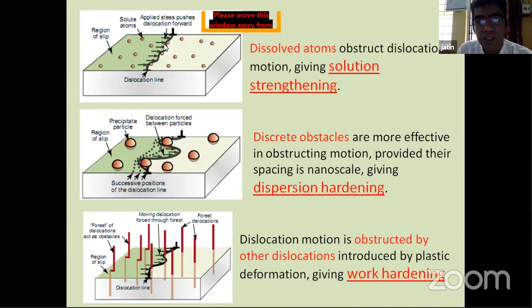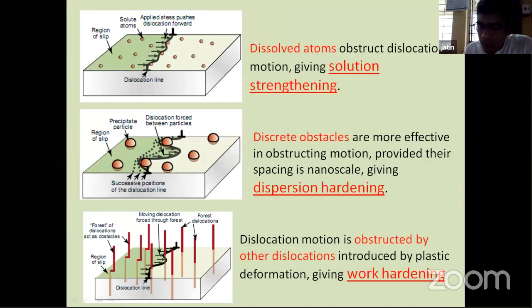Now there are three ways by which this is happening. Either your atoms are dissolved, but they do have some physical features present inside the material. When you deform the material, these dissolved atoms resist the deformation force, and your dislocation line is obstructed here. So you call it solution strengthening. When you have discrete obstacles of nanoscale dimension, you will see that they also obstruct the deformation force, which you call dispersion hardening. You can also do mechanical work on the material in order to create dislocation jungles. When you want to deform this material, dislocation is going to stop dislocation. See here, the small particle is the precipitate, of bigger dimension, and this is a dislocation jungle. All have different names: solution hardening, dispersion hardening, and work hardening. This is the way you can impart strength in your material.